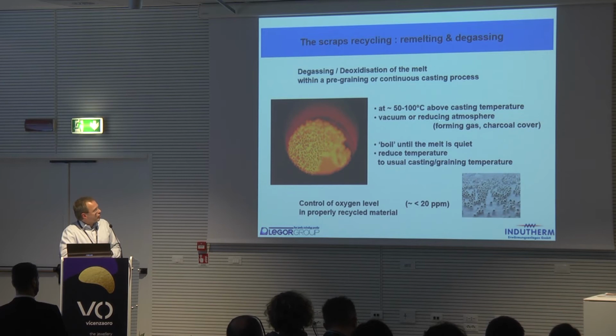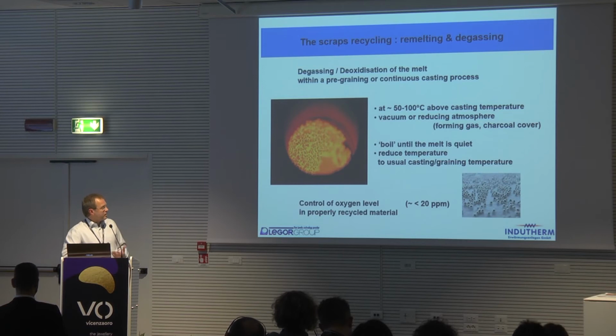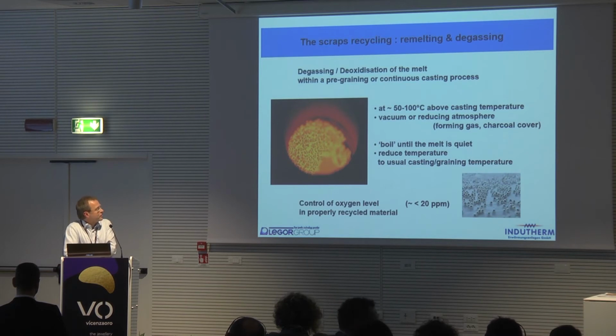Applying a vacuum or an even more reducing atmosphere can also be done on certain types of equipment. We will observe the melt and see the gas bubbling out. Then we can reduce it once the melt is quiet and go to a usual casting or graining temperature. So a low oxygen level can thereby be obtained, also for properly recycled material, and that will translate greatly into improved quality of the casting.